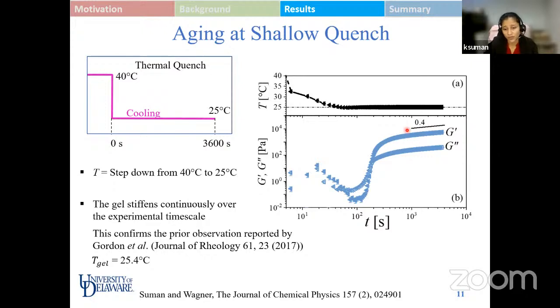This is consistent with what has been reported in the literature, and this slow growth in the modulus value has been studied to be evolution towards a more final homogeneous structure of the gel. So with having established our results are consistent with the literature, we now move on to probing the system at